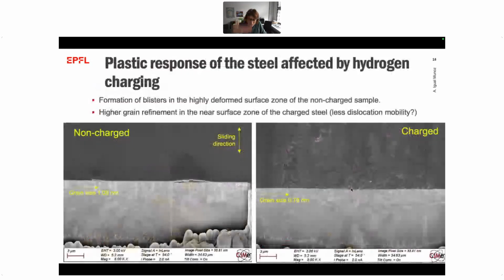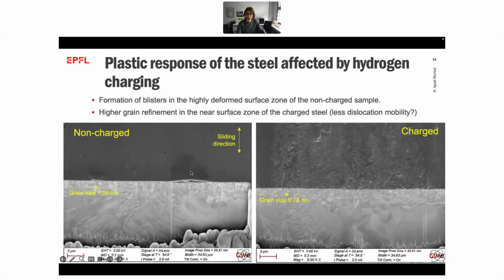We went a little bit further in the analysis. So now we cut a cross section perpendicular to the sliding direction. So this is the wear track. We do a FIB cross section, and then we can see not only the surface, but also the subsurface, what happened inside the material. And what we observe is this kind of formation of blisters on the non-charged sample, with even local delamination of this very smeared material. And in the charged sample, the hydrogen uptake blocks somehow the deformation, and then what it generates is more accumulation of strain, so a little bit of embrittlement of the material, and a little bit higher grain refinement compared to the non-charged sample. So we see differences even if we have the same shear.